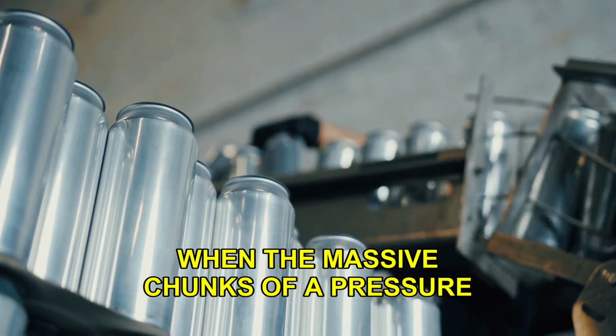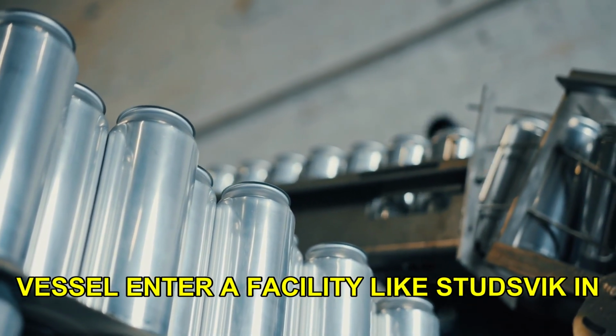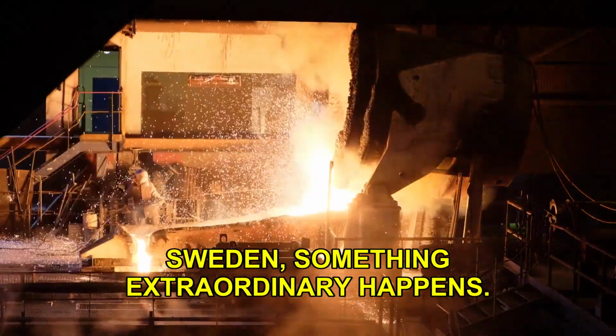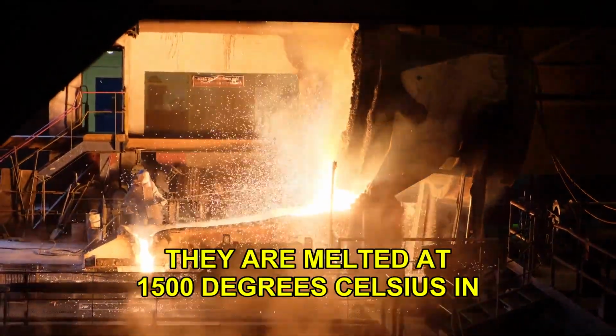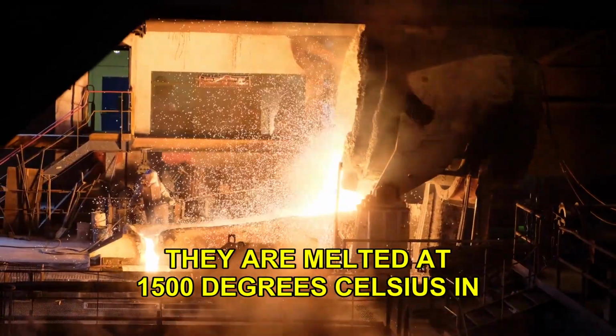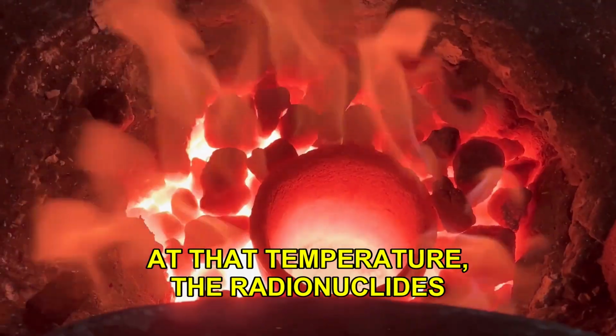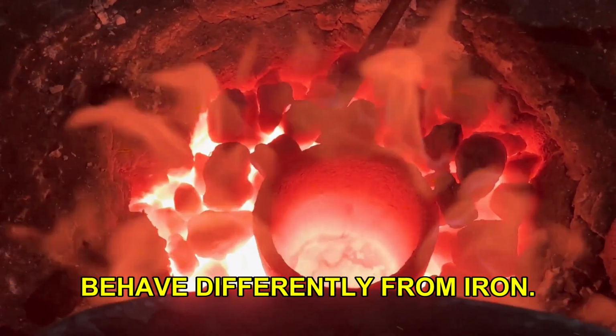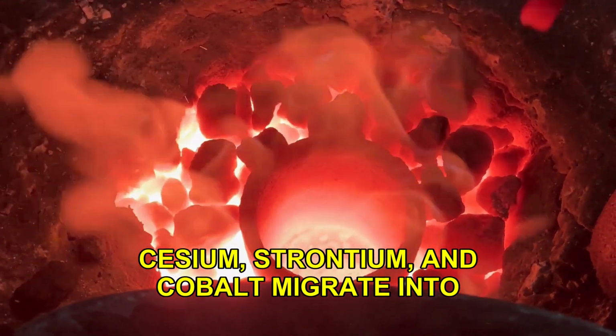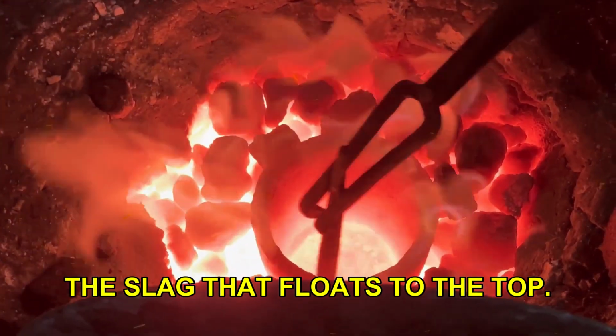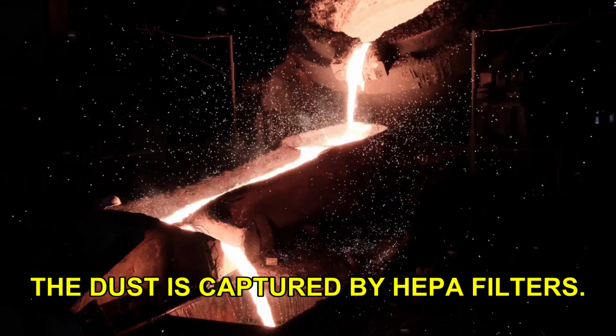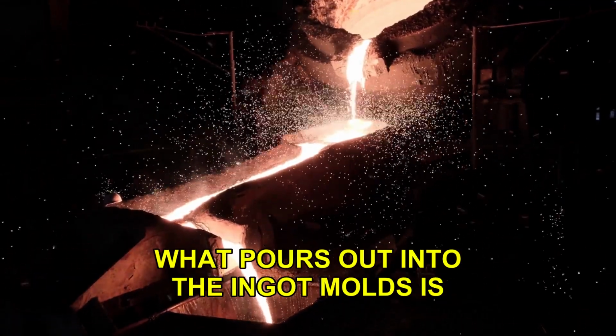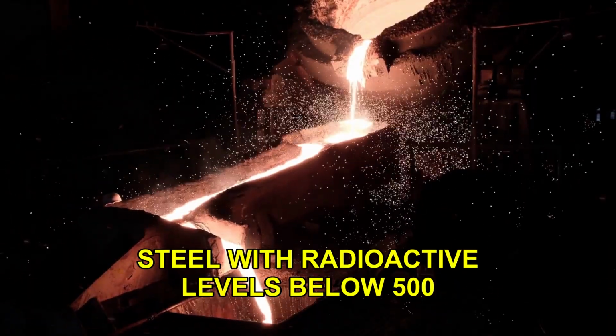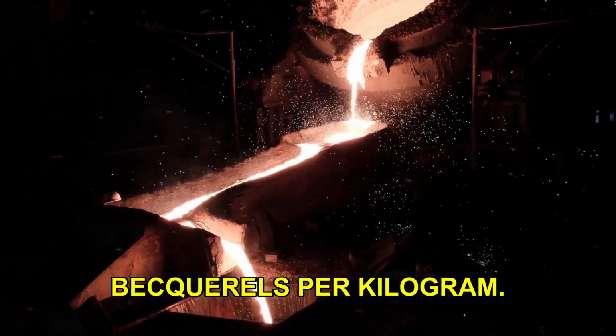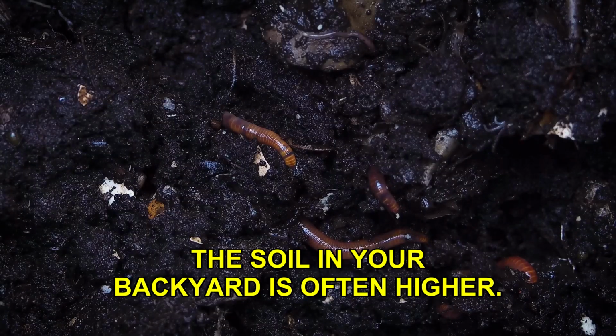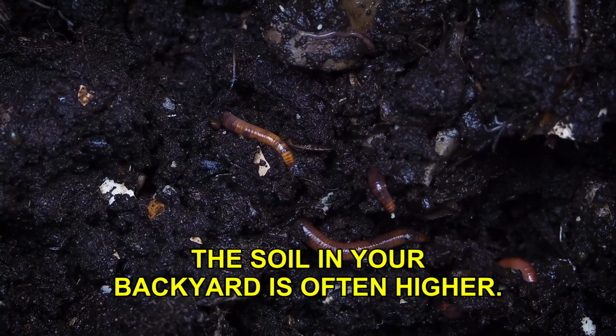When the massive chunks of a pressure vessel enter a facility like Studsvik in Sweden, something extraordinary happens. They are not just washed. They are melted at 1,500 degrees Celsius in an induction furnace. At that temperature, the radionuclides behave differently from iron. Cesium, strontium, and cobalt migrate into the slag that floats to the top. The dust is captured by HEPA filters. What pours out into the ingot molds is steel with radioactive levels below 500 becquerels per kilogram. A banana has about 125. The soil in your backyard is often higher.